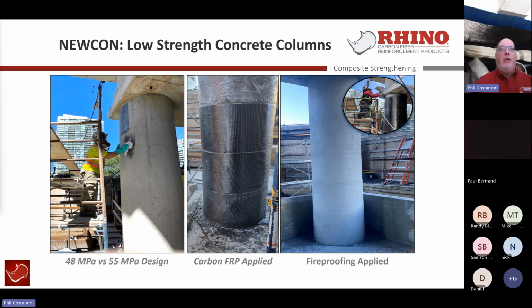You need to re-strengthen these columns. In this case, it was a new con. Whoops. And again, it happens. Like I said, everybody has a bad pour day. Your iron workers have a bad day placing bar in the wrong location on a slab or a wrong location in a wall, and it adversely affects the strength of it and gets caught by the EOR. We can come up with the calculations to utilize our unidirectional confinement application for carbon fiber, apply it up against.